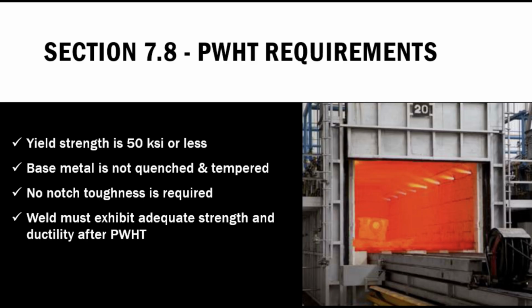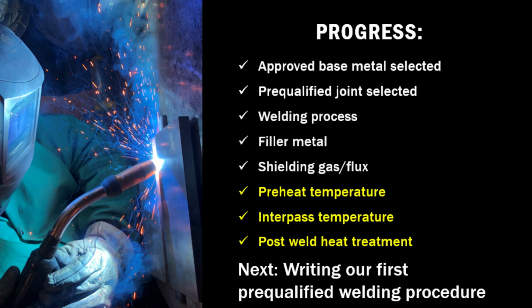Post-weld heat treatment is only pre-qualified if all of the following are true. Yield strength is 50 ksi or less. Base metal is not quenched and tempered. No notch toughness is required, and the weld exhibits adequate strength and ductility after post-weld heat treatment. This completes Lesson 3, and we are now ready to write your pre-qualified welding procedure.